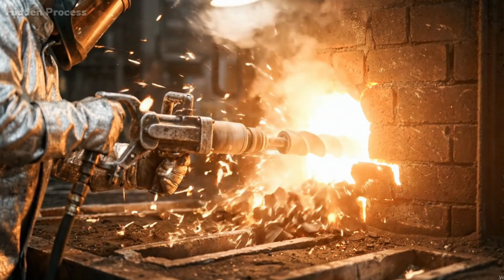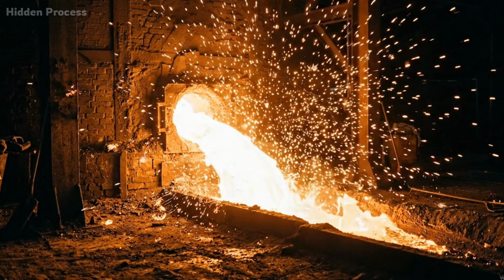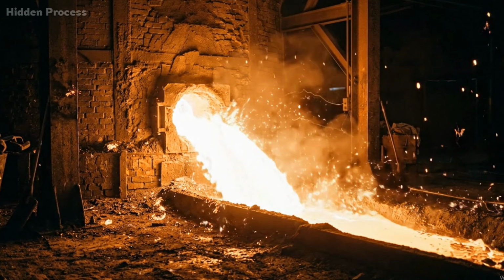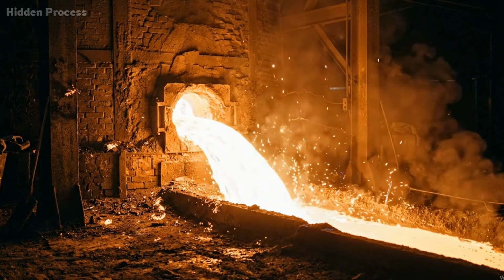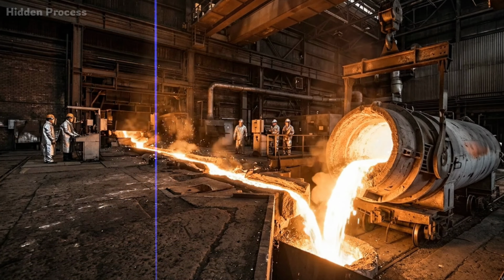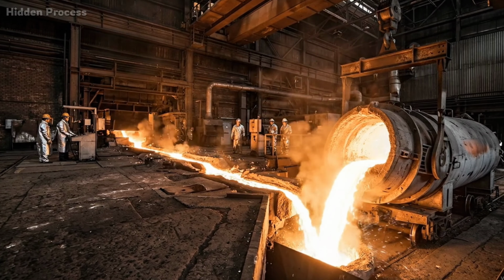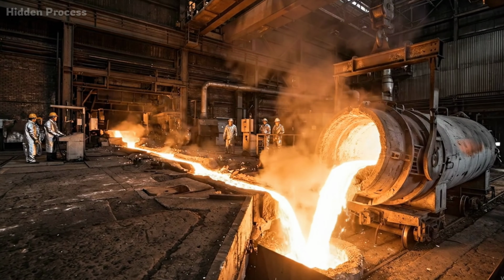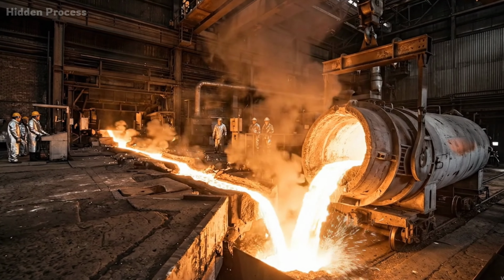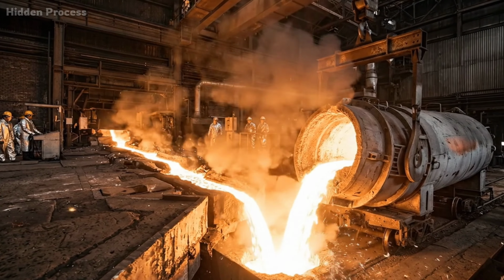And then it happens. Liquid iron, glowing orange-white at 2,700 degrees F, pours out in a river of molten metal, flowing down channels called runners into massive torpedo-shaped ladles. These ladles hold up to 300 tons of liquid iron at a time.